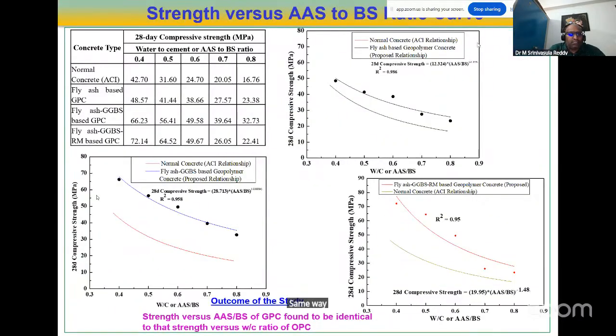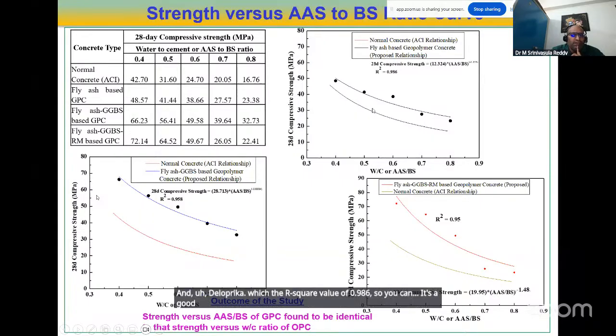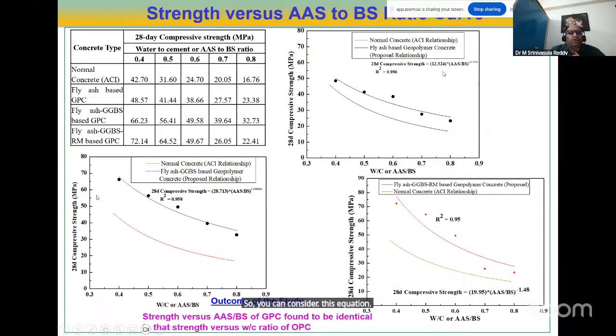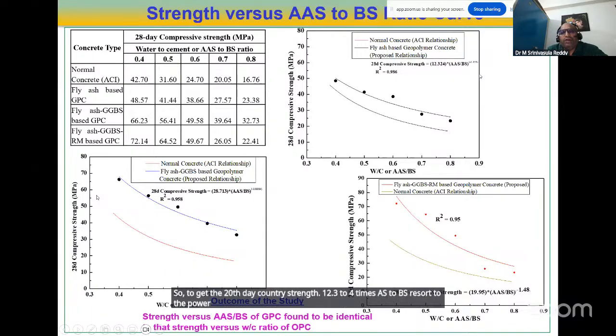In the same way, you can see this is the strength to water to cement ratio as per ACI code. You can see here fly ash based alone. These are my 5 points: 0.4, 0.5, 0.6, 0.7, 0.8. And I developed a curve with an R square value of 0.986. So it's a good relation, and you can consider this equation to get the 28-day compressive strength: 12.324 times AS to BS ratio to the power minus 1.359.